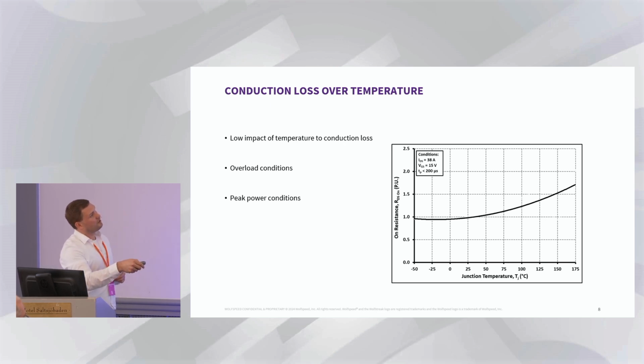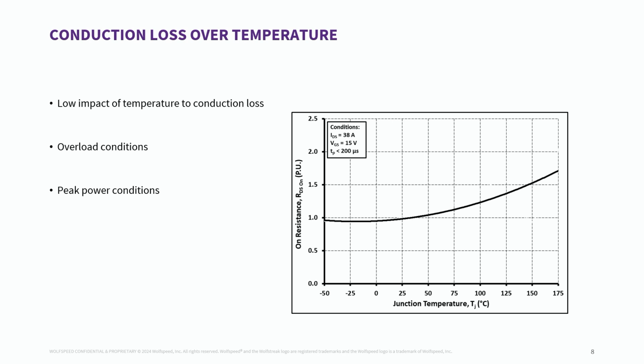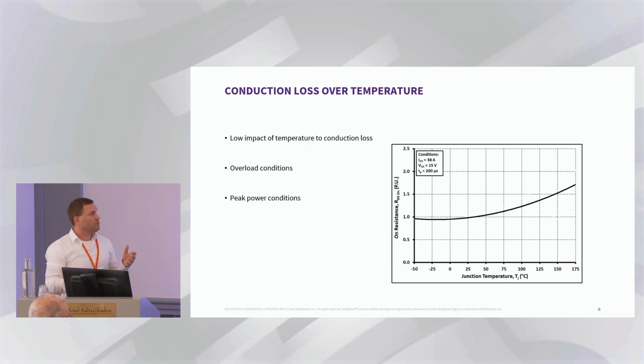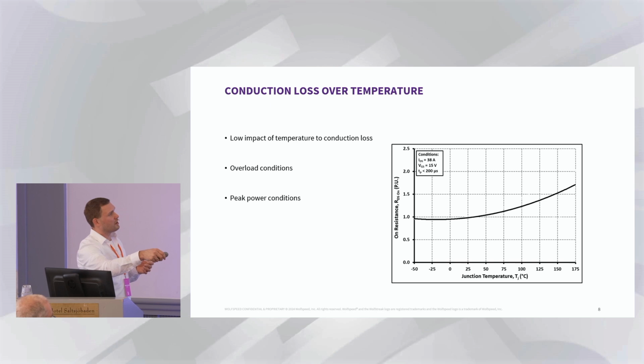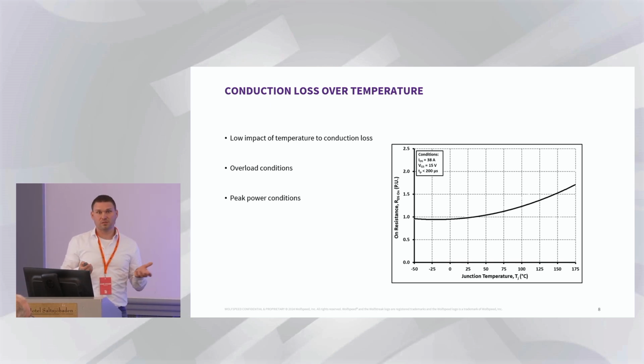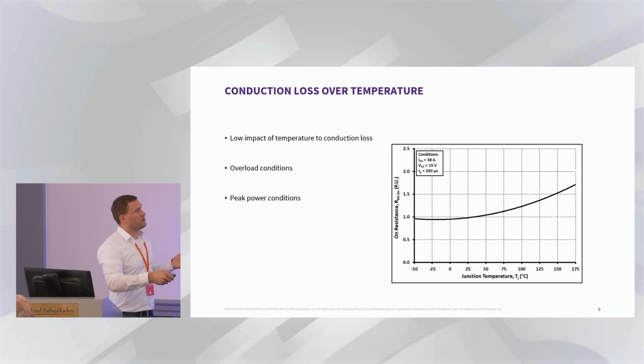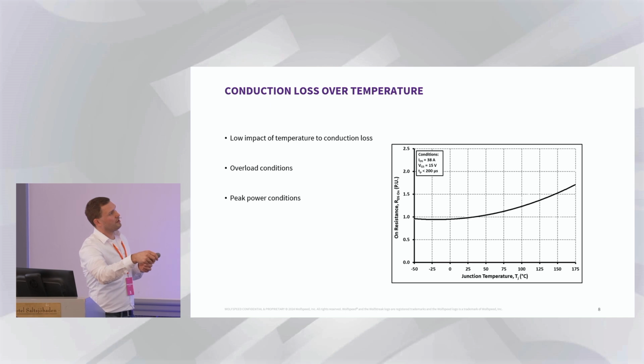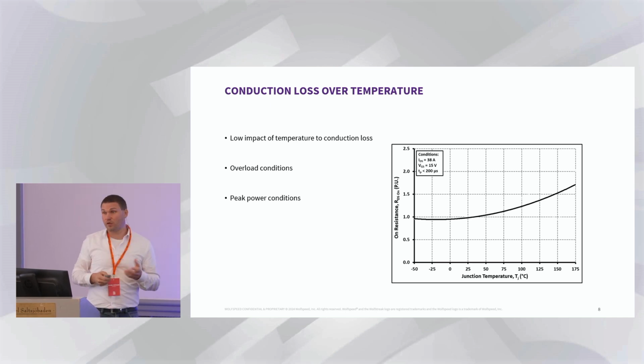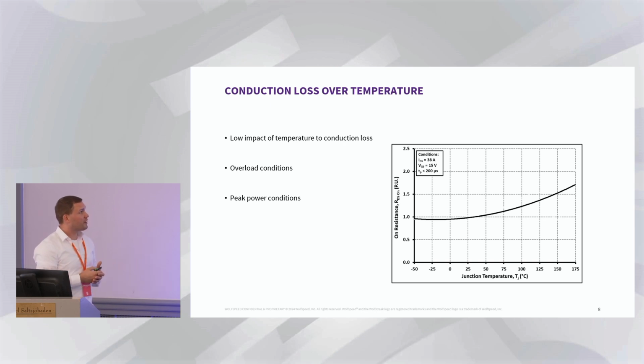Yeah, this is the RDS(on) over temperature that you can see here. At room temperature, this is the rated RDS(on). And we have about 1.7 roughly when it comes to 175 degrees C. Yeah? This is quite helpful if you design your system. You always have the marketing value of the RDS(on) at room temperature, which is not really helping in the application because your system doesn't operate at room temperature. What really matters is the range of 125, and then for overload conditions also up to 175 or even higher. So the devices are really nice for high power applications and conditions, since the RDS(on) is really quite stable over the temperature.